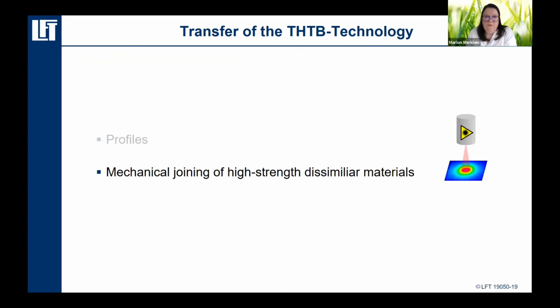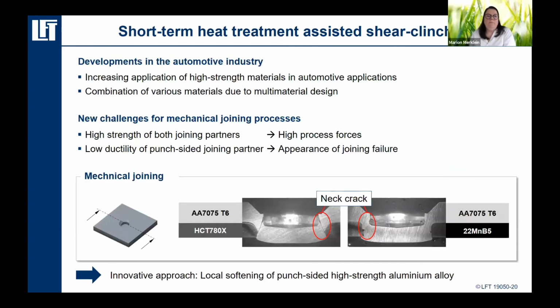Many of the companies working in this field complain about the limits of joining different materials, especially steels and aluminum alloys, and especially if we work with high-strength steels, as for example an HCT 780, or also a hot stamp material with a high strength of about 1500 Newton per square millimeter. In all these cases, the ductility and also the strength of the aluminum alloy are not sufficient to work with such a joining technology. And the most important point, of course, is that with an increasing strength of the aluminum alloy, for example, if we use a 7000 series, we have a limited ductility.